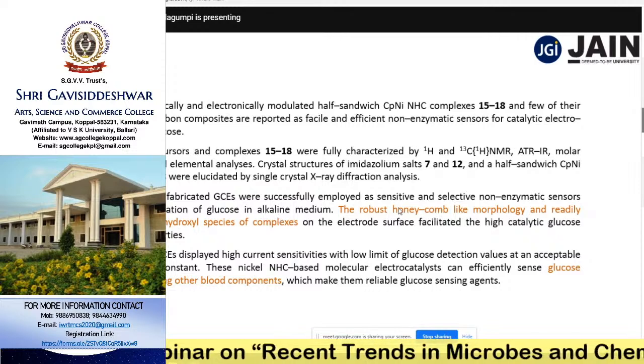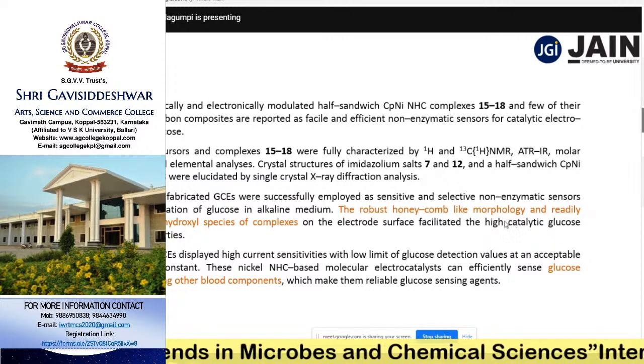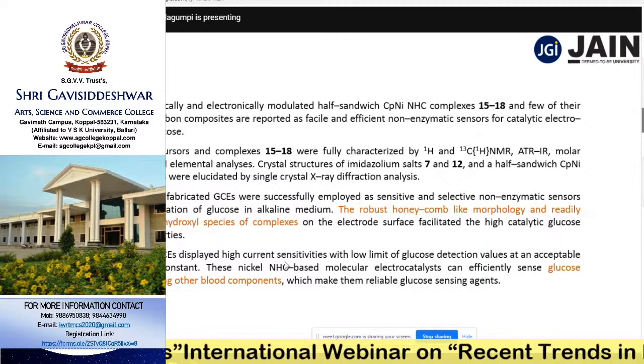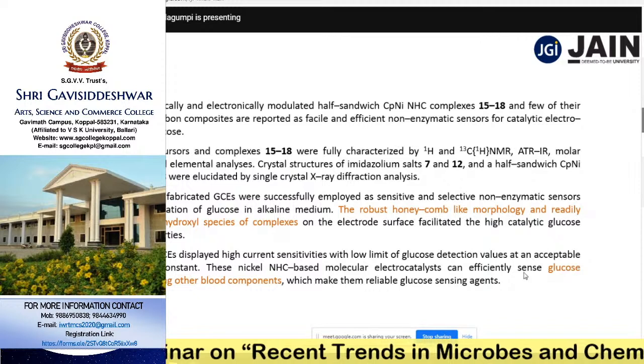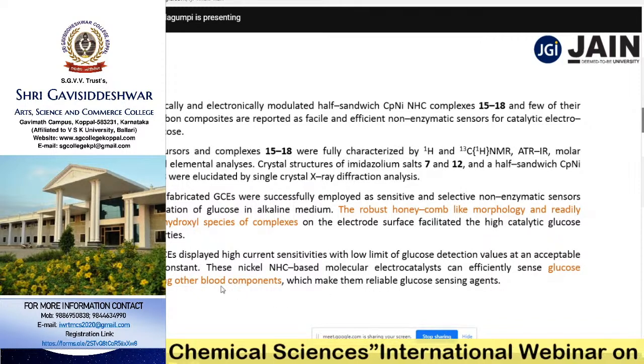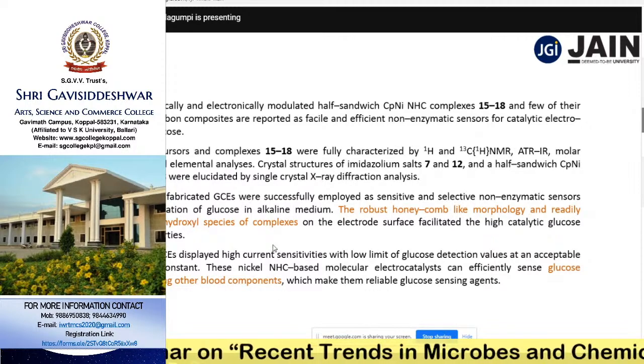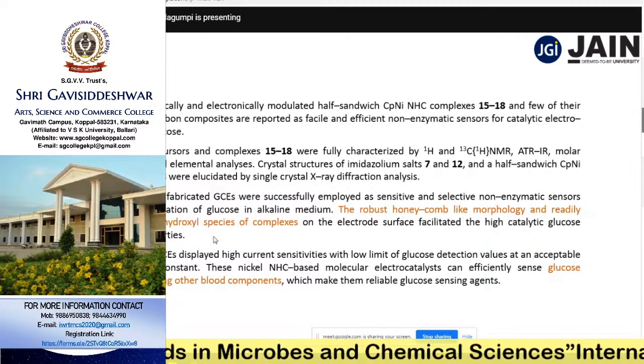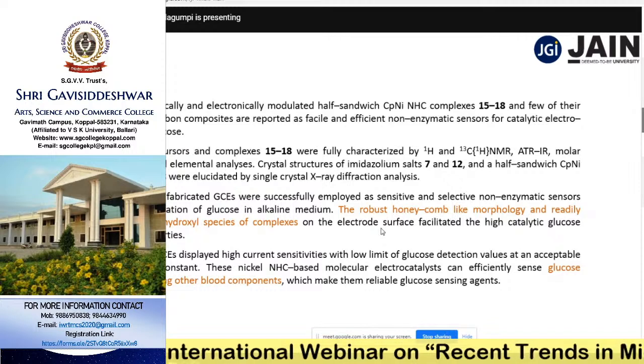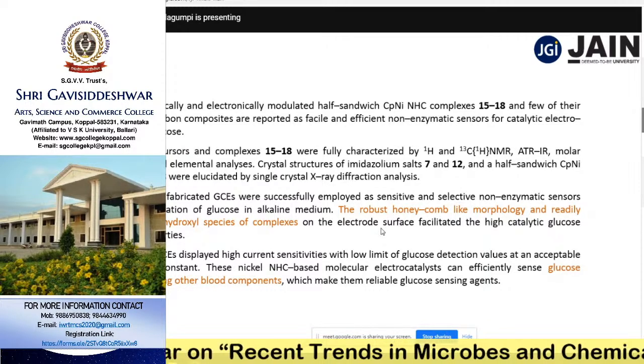And these complexes were found to be effective glucose sensing materials because of their robust honeycomb-like morphology and the readily evolved nickel hydroxyl species of the complex. These are intermediates actually. And finally, these can be used as effective glucose sensing materials because they are selective towards glucose, even in the presence of other blood components like ascorbic acid and uric acid. So this is about the nickel NHC complexes and their electrocatalytic application. And this is the first ever report on nickel NHC complexes, or nickel organometallic complexes, being used for electrocatalytic applications. Dr. Shashikant?